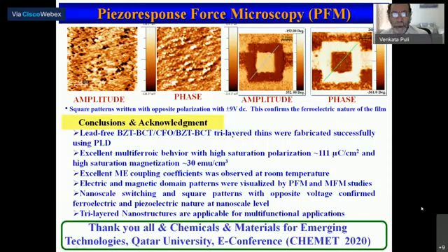As I said, perfect square patterns were shown. In conclusion, these lead-free ferroelectric and ferromagnetic tri-layers were fabricated successfully using the PLD technique, and excellent multiferroic behavior with high saturation polarizations and high saturation magnetizations was recorded. Excellent magnetoelectric coupling was observed, and the PFM contrasts were seen. Excellent electric and magnetic domain patterns were visualized using the PFM technique and MFM studies also. Because of time constraints, I am not going deep. Nanoscale switching and square patterns with opposite voltage confirmed the ferroelectric, piezoelectric, and piezomagnetic nature of these artificial multiferroic films at the nanoscale level. The tri-layer nanostructures are applicable for multifunctional applications.